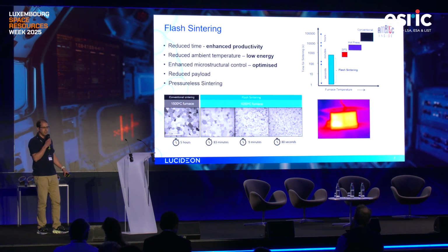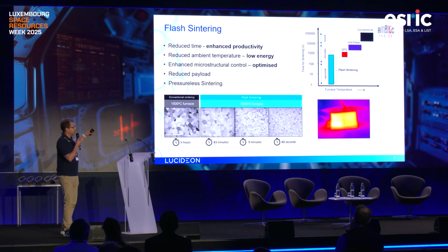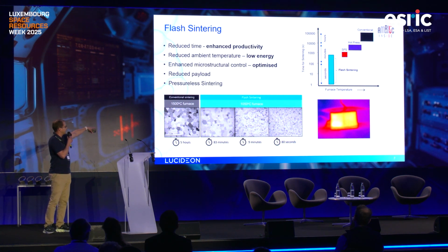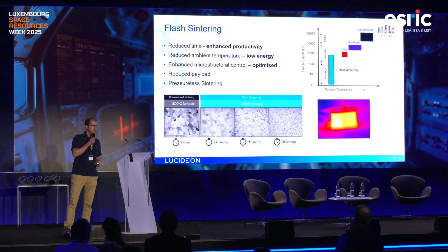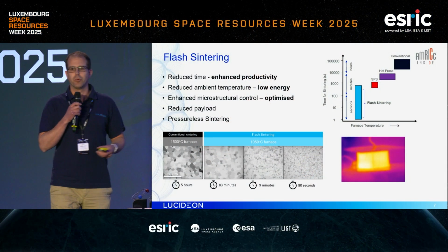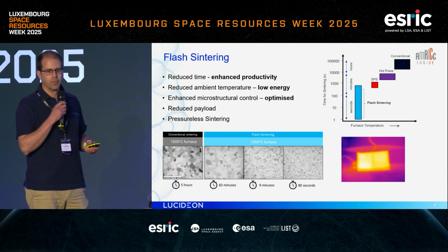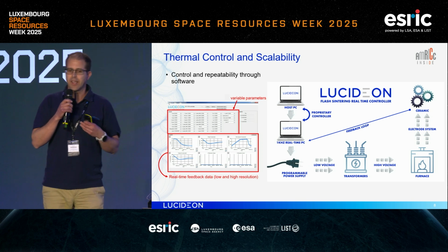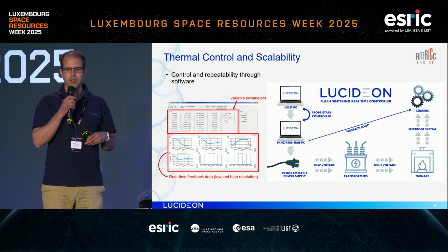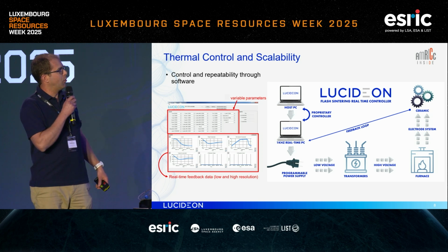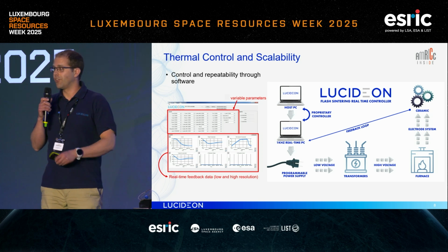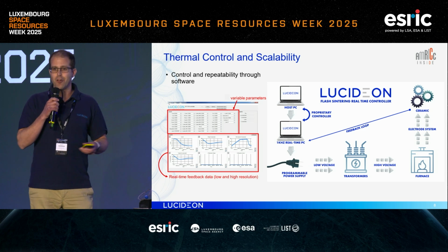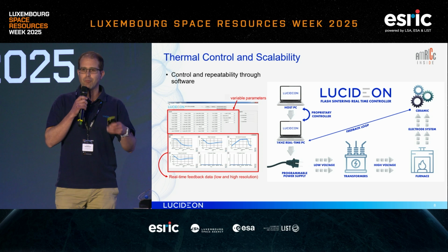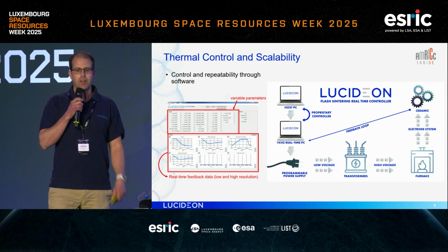So along the bottom here, we're seeing different microstructures for the same density versus a conventionally sintered sample, where we see the grain size. So flash sintering in some of the academic papers is always headlined as, you know, sintered in under 5 seconds. We don't really care about that in the sense of that headline. It can be minutes, it can be hours if we want to. Depends what we're trying to get out and how we want to manipulate that material. The way in which we do that is we've tried to make it a very scalable technology through enhanced thermal control, and that uses a proprietary software that we've written. It's a non-linear real-time control software. It's not as simple as just current, voltage and time. There's over 20 sort of field parameters that we can manipulate, so ramp rates, pulses, hold times, things like that, and that's fed through to the system.